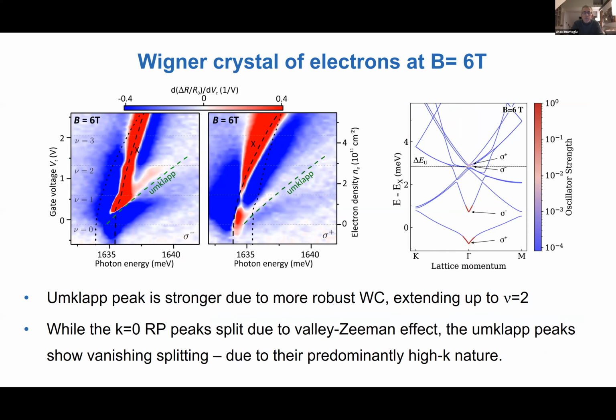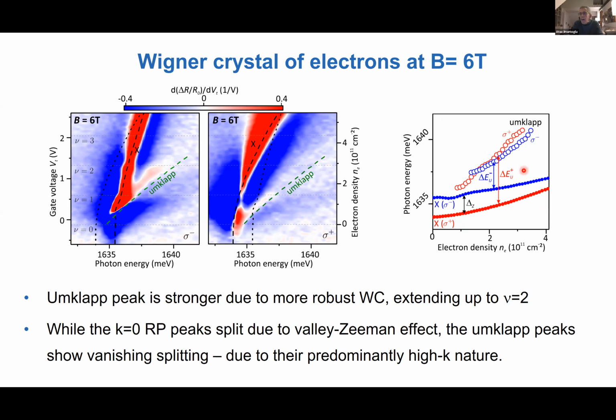Okay, so finite magnetic fields, in this case 6 Tesla. So you see that Umklapp peaks, particularly in one polarization, become substantially stronger. And what is happening here is that due to the Valley-Zeeman effect, the k=0 exciton resonances split. But if you look at the energy of the Umklapp resonances, they hardly show any splitting. And this initially was surprising to us, but then by invoking the nature of these Umklapp resonances as arising from the transverse polarized excitons, we had an explanation. Basically, the Umklapp resonances, whether they are sigma plus or sigma minus, arise from large momentum excitons, which are polarized in plane. So in that sense, they're insensitive to the Zeeman effect, and therefore their energy hardly gets modified.